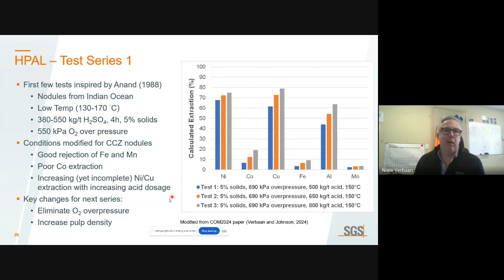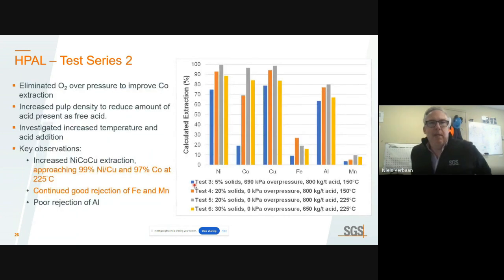And we quickly decided, okay, let's eliminate this oxygen overpressure. We were quite concerned that it contributed to the poor cobalt recoveries. We played around with pulp density, and that's really what this test series is about. And here we see, again, extraction versus metals here, that under certain conditions, we were able to get pretty high nickel extraction. We're close to 100%. Same for cobalt, same for copper. But we weren't quite happy yet with the rejection of these various impurities. But making good progress here.